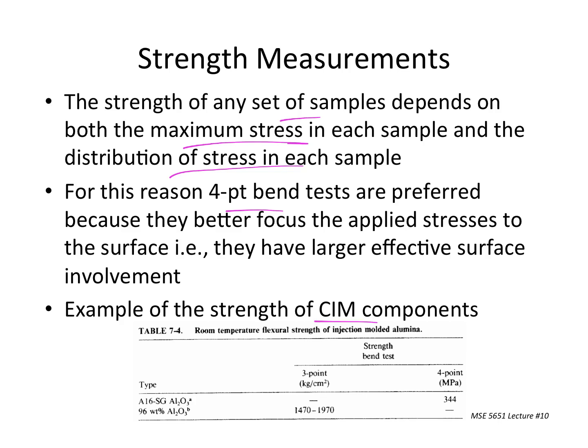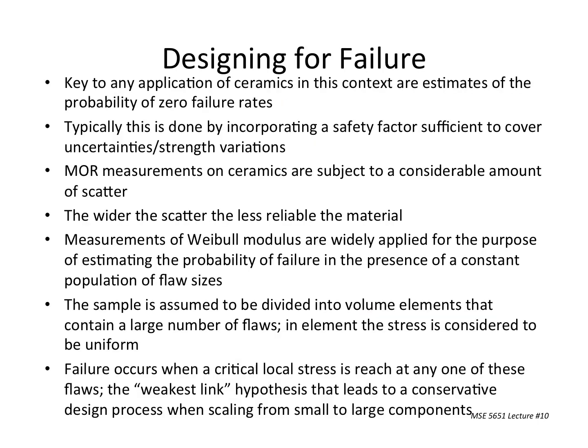And the strength of these components, this is showing you for a couple of different kinds of alumina, different values of strength. I'm going to talk about that. But what we do is we design for failure. All right, so these Biolox alumina parts, they have a failure rate of 0.004%. All right, so that means that if you get one of these things in your hip, you have a 0.004% chance of that thing failing. So out of 1,000 parts, maybe 4 will fail. All right, maybe. Okay, and so what we do, we incorporate safety factor. We do a ton of work on modulus of rupture, and we see that the wider the scatter, the less reliable the material is. I'll show you an example of that in a second.